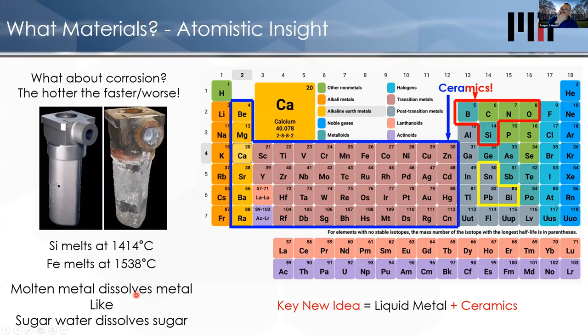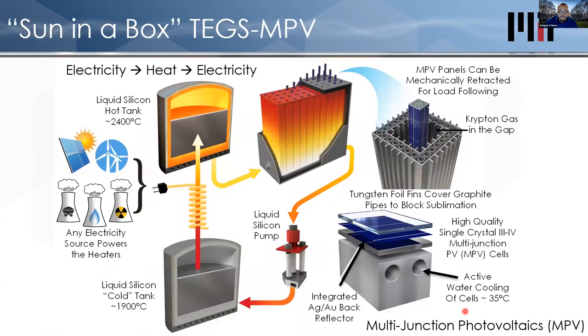So imagine trying to store water in a tank made out of sugar, right? It's going to dissolve the walls, and very quickly the tank wall will go away and all your sugary water will go everywhere. So our insight was, instead, we should be looking at materials where you take one of these elements and pair them with one of these elements so that you make a ceramic. If you do that, then you can actually form materials that are thermodynamically stable with respect to certain liquids, certain liquid metals. You can actually make something that has no chemical interaction and forms no corrosive byproducts if you start with a ceramic. So our key new idea that we brought here was the idea of doing liquid metal with a ceramic-based infrastructure. And ceramic-based infrastructure may sound difficult to make. It is, but we have overcome a lot of the challenges with doing that.